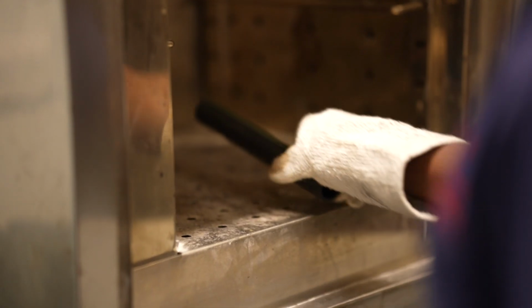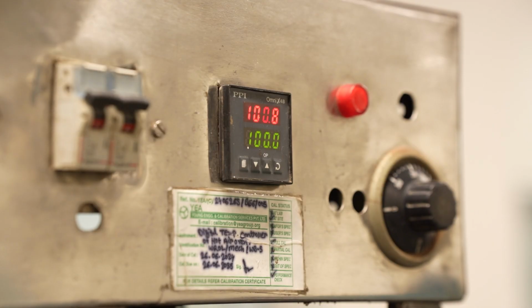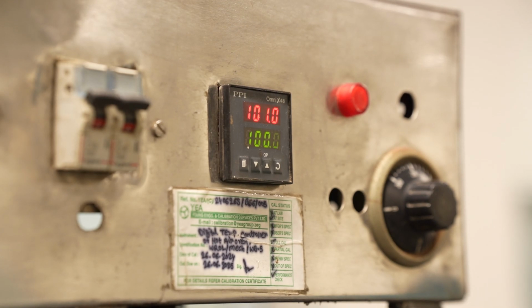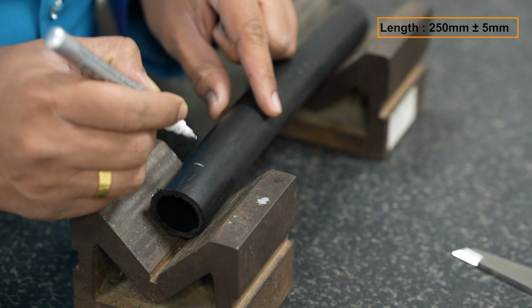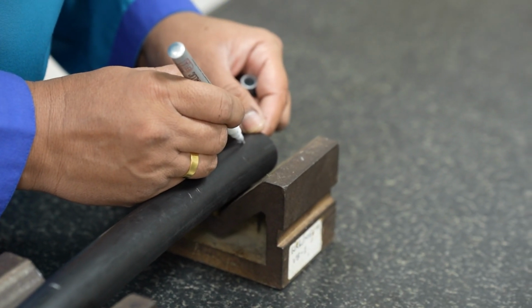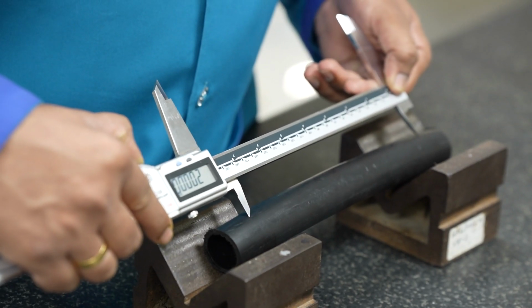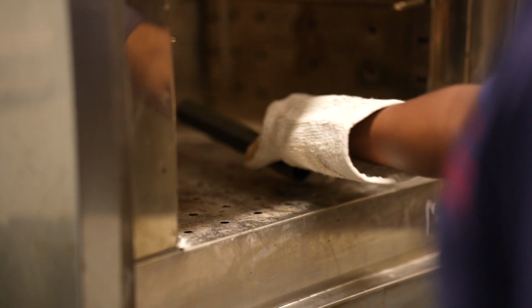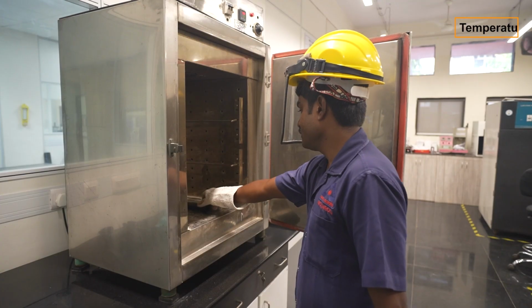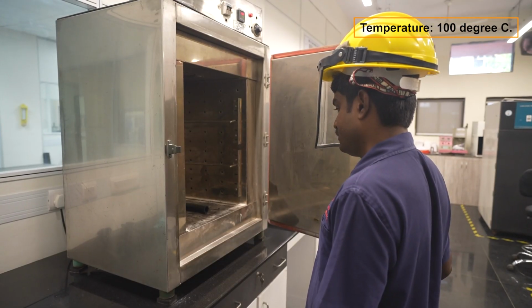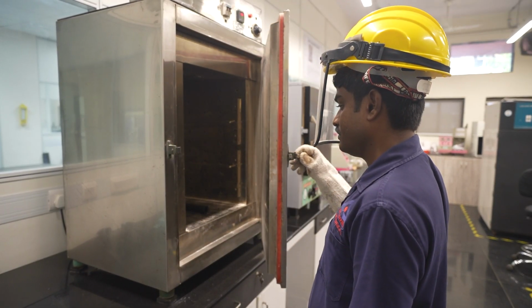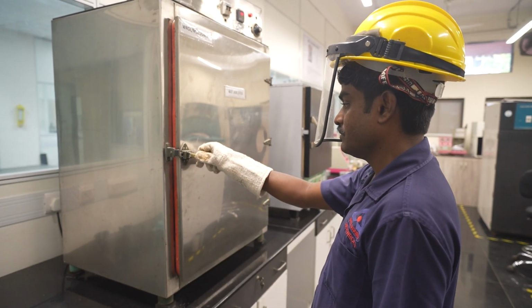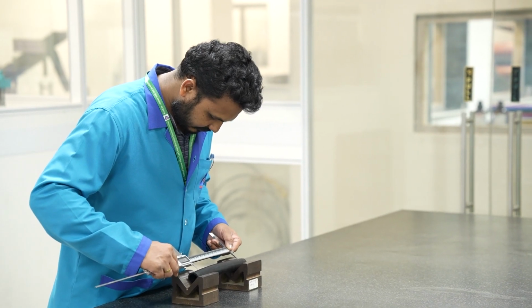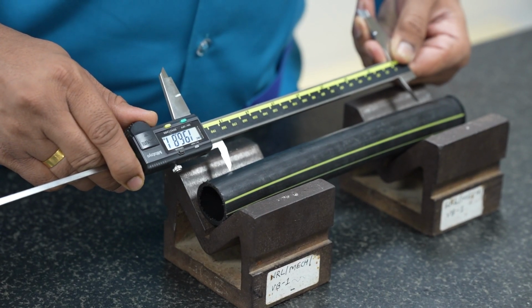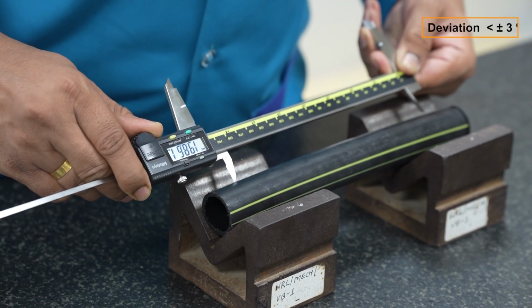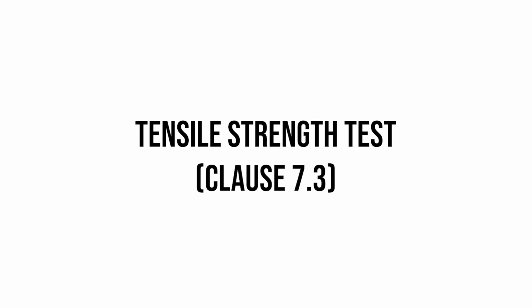in irrigation system. For reversion test, hot air oven at 100 degrees Celsius plus minus 2 degrees Celsius is required. A 250 mm plus minus 5 mm pipe length is marked at 2 points 200 mm apart using a vernier caliper. The test piece is then placed horizontally in an air oven at 100 degrees Celsius plus minus 2 degrees Celsius, ensuring no hindrance to dimensional changes. After cooling, the dimensional change in the longitudinal direction is measured, and any deviation from the initial length should not exceed plus minus 3%. The next test is tensile strength test.